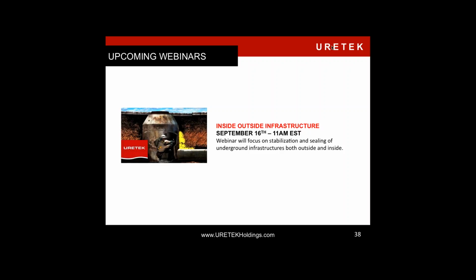One of the things to keep in mind is we do not want to inject when the ground is frozen. Reason being, if you have trapped water there, you're going to have a false void. So you're bringing that into the equation when you lift, and then once that water thaws out, you're going to have some post-injection settlement. Typically, usually fall up, usually working in environments about 40 degrees on up. Yes, we can make provisions to work in freezing temperatures if need be.